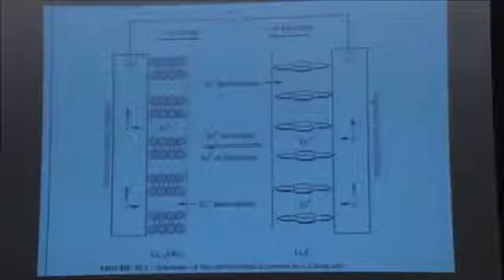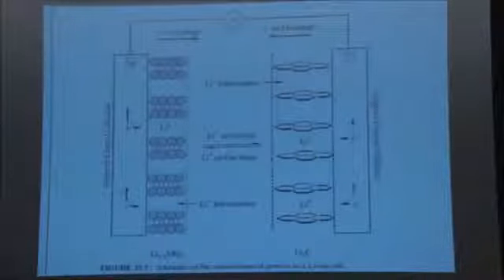When the lithium-ion battery is assembled, the negative electrode is graphite, the kind that would be in your pencil. And the positive electrode is a lithium transition metal oxide that's synthesized in the air at high temperature. It's stable in air. So both electrode materials are stable in air. You can build a battery in the open air. As soon as you put it together and start to charge the battery, you force electrons in this sense to the right, and the corresponding lithium ion hops out into the electrolyte and moves to the graphite where it gets intercalated. That charges the lithium ion cell.